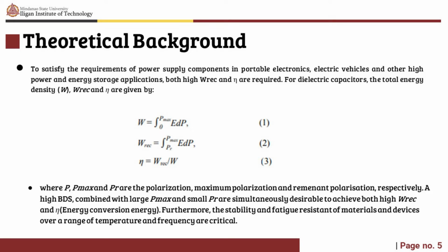So now let's proceed to the theoretical background. To satisfy the requirements of power supply components in portable electronics, electric vehicles, and other high power and energy storage applications, both high WREC and η are required. For dielectric capacitors, the total energy density W, WREC, and η are given by these equations, where P, Pmax, and PR are the polarization, maximum polarization, and remnant polarization, respectively. A high BDS combined with large Pmax and small PR are simultaneously desirable to achieve both high WREC and η. Furthermore, the stability and fatigue resistance of materials and devices over a range of temperature and frequency are critical.